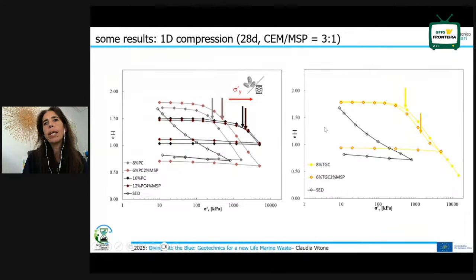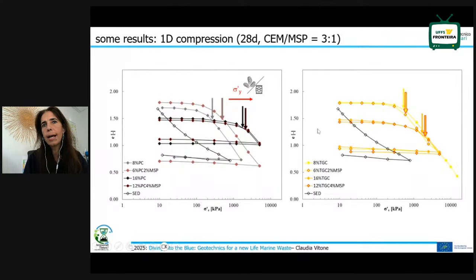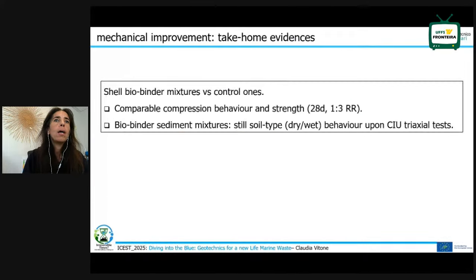And the story practically is the same if we use the steel slag cement, which is a greener solution. So essentially, the take-home evidence in all this is that we have a very good performance of the new mixtures, because we are recording comparable compression behavior and strength after 28 days, in particular when we replace 1/3, in terms of ratio, between the mussel shell powder and the cement. Essentially, they are still behaving as a soil, in particular during triaxial, but also unconfined compression strength.